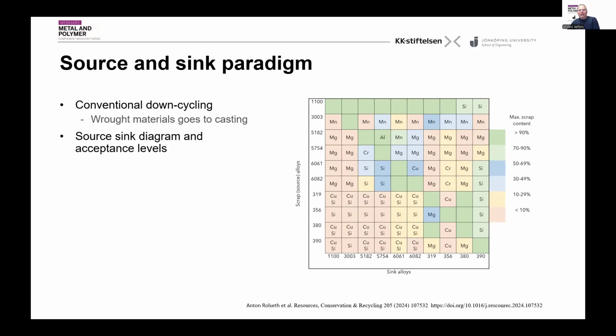And if you talk about the main elements, we can see that one of the more troublesome is magnesium. And then, knowing also that iron is an issue, if you remember here that aluminium, iron, magnesium was one of the ternary phase diagrams that is an issue. So already at this point, we can say that the insufficient description of the aluminium, iron, manganese system actually hinders us from effectively utilizing this, because we have the uncertainties of the iron enrichment being seen in scrap. So managing a good source and sink system is difficult.